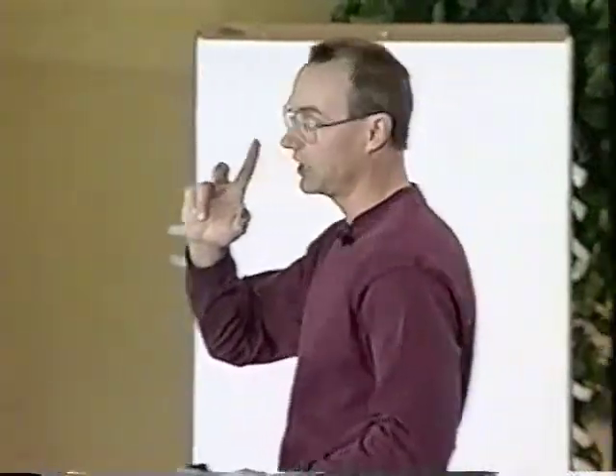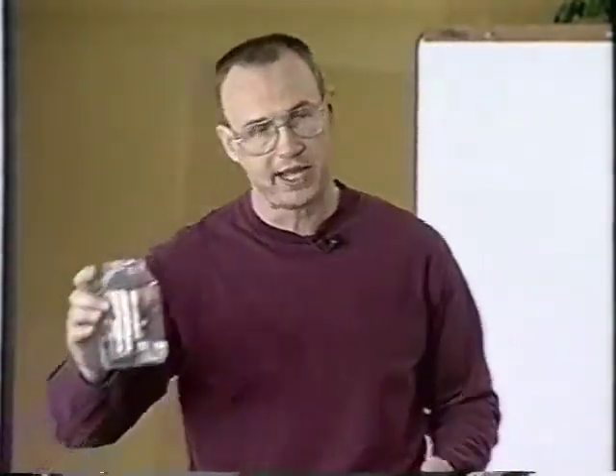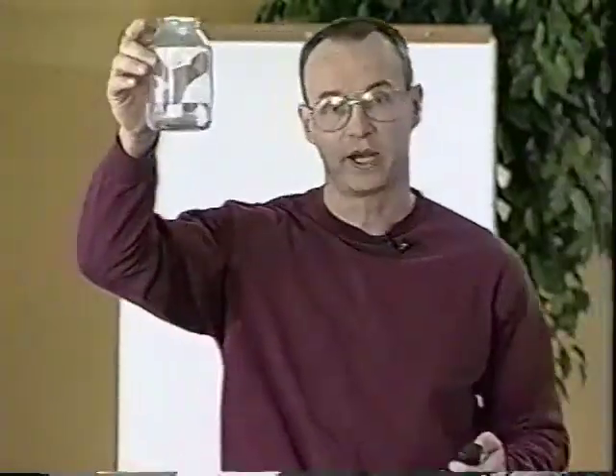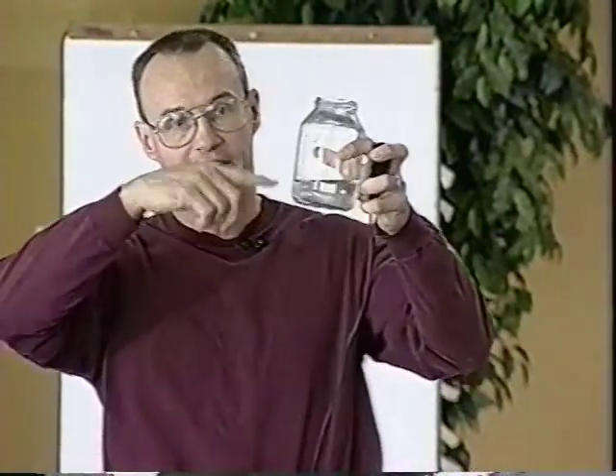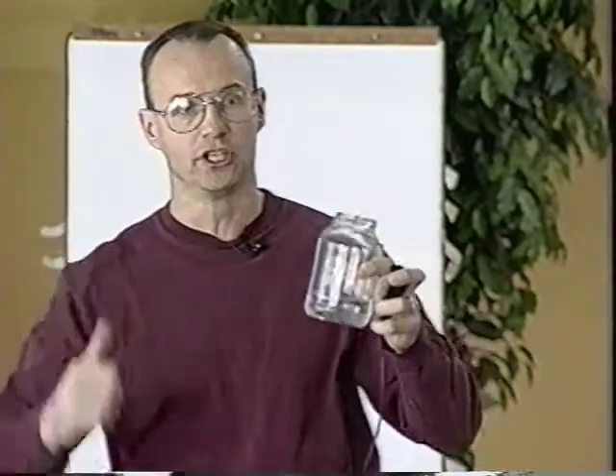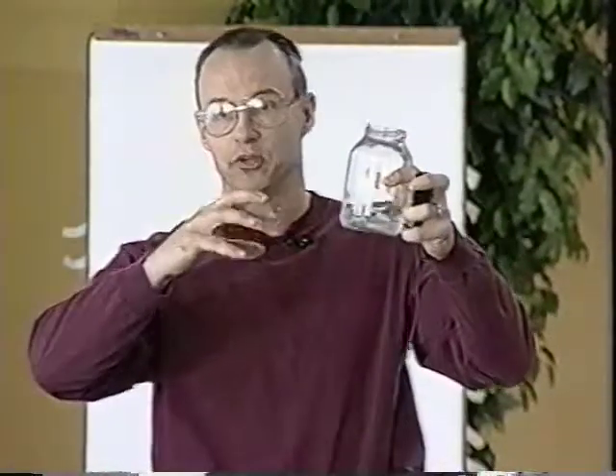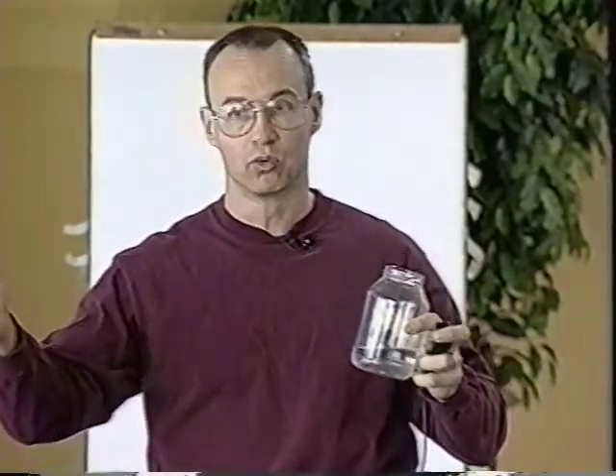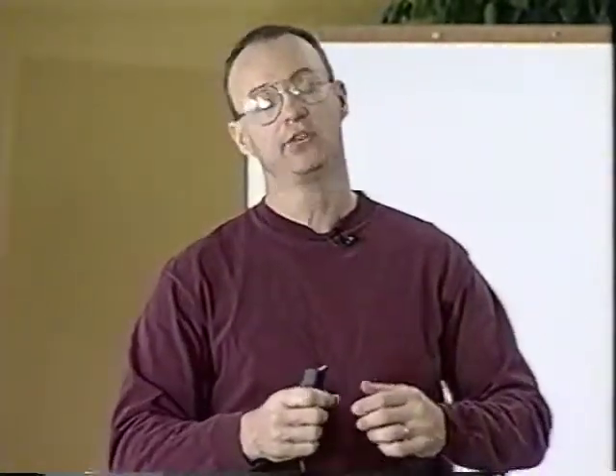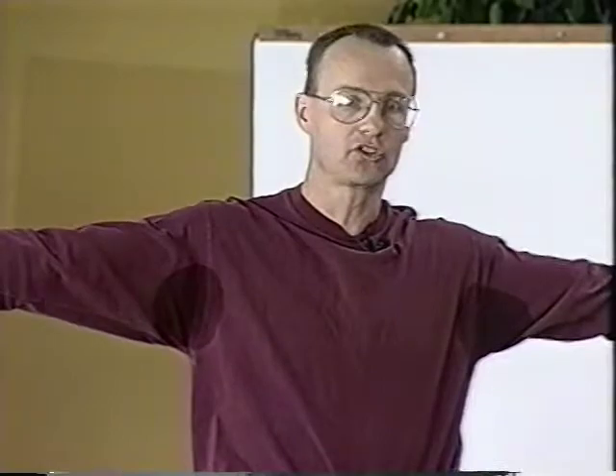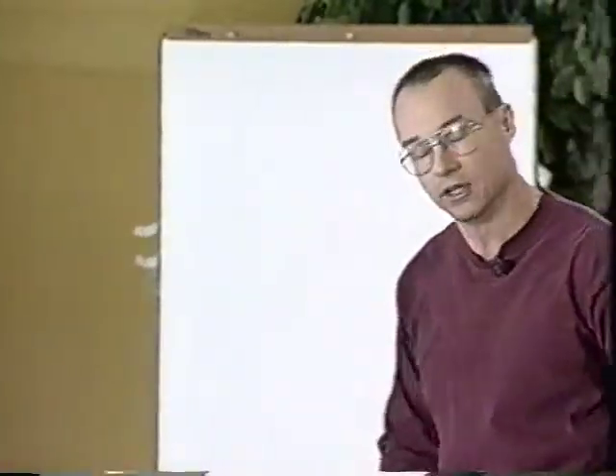And as I was saying, that steel is saturated with oxygen. There's a certain amount of oxygen now left over in the steel, and that oxygen is bad. If you can imagine what a glass of pop looks like with all the little carbonated bubbles floating around in the pop, well, that's what oxygen is in steel. It's a bunch of little oxidized bubbles floating around in steel, and if you roll those oxidized bubbles out, and again now we're thinking about a bubble, okay, that's in a slab of steel. If you roll it out in a rolling mill, that little bubble will go like that, and we'll have a big old sliver down in the delivery end of the cold mill.